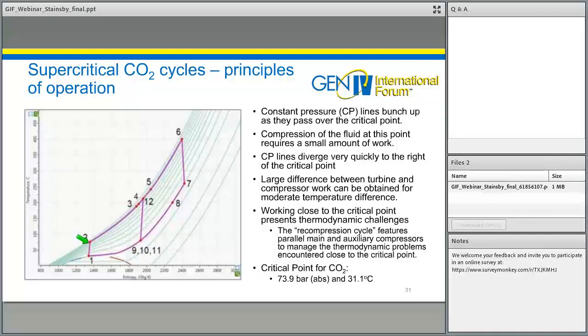So this requires a small amount of work. We are doing some compression here away from the critical point, but we're only compressing something like 40% of the total mass flow of gas going around the circuit. So even though the height difference between there and the turbine there and there are very similar, we've got 100% flow going down there, and we've only got 40% of the flow going up here. So we still win out overall in terms of work ratio. It's quite a complicated cycle, with all these state points referring to the different recuperators.